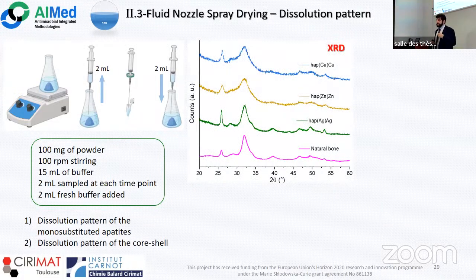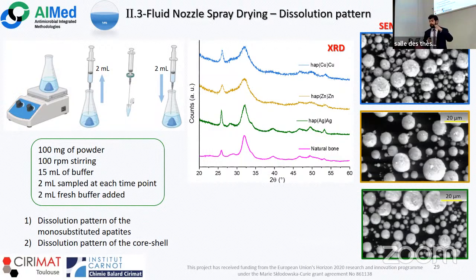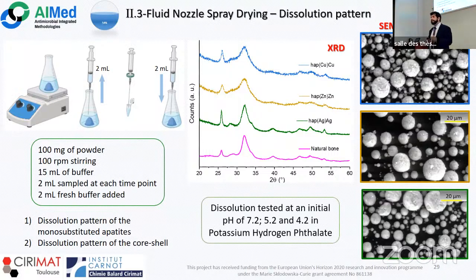Before studying the core shell systems, we studied the monosubstituted spray-dried systems. So we studied three particles, copper, zinc, and silver, spray-dried to have, as you can see, the same morphology and the same size distribution. And we studied the dissolution in potassium hydrogen phthalate at three different pH: 7.2, which is close to physiological, 5.2, which is close to the pH we experience in an inflamed site in the body, and 4.2, which is an extreme condition that is also good for us to study to speed up the dissolution of the particles.